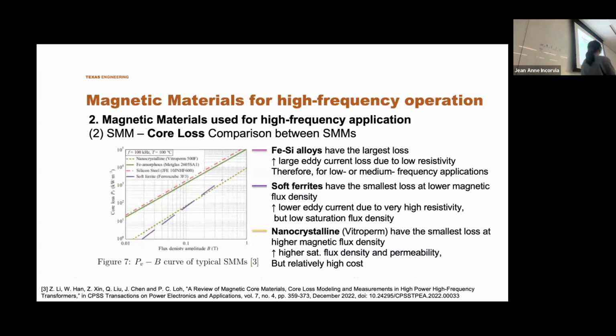So lastly, I'm going to compare the important core loss between the SMMs. As you can see from this diagram, the iron silicon alloys have the largest loss, this one. The soft ferrites have the smallest at the lower magnetic flux density here, and the nanocrystalline alloys have the smallest loss at the higher magnetic flux density.